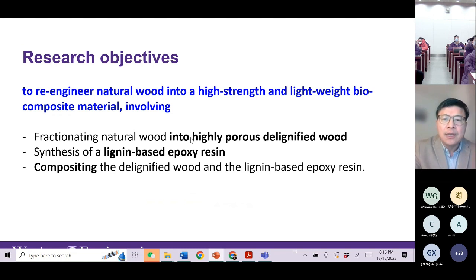We use ultrasonic, so we can make the extraction more efficient to remove lignin and make a porous delignified wood. And then we turn the extracted lignin from the wood into epoxy resin. After we produce the epoxy resin, we impregnate that resin back into the porous wood, so we can make a composite of delignified wood with the lignin-based epoxy resin. In this way, we address those three challenges.